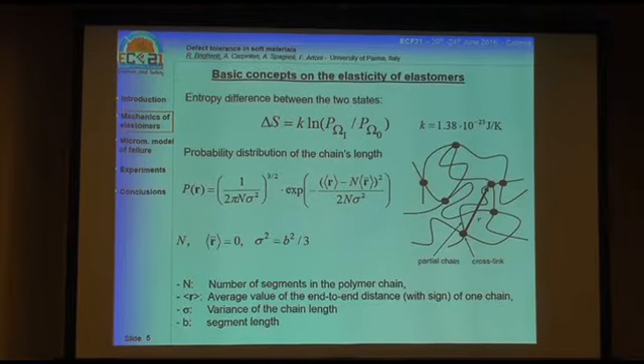So typically, this kind of material is described by the classical rubber elasticity theory that takes into account the probability distribution of the so-called R² distance, which describes the average distance between the crosslinks that exist between the polymeric chains. This is the standard probability distribution used in this case, which is a Gaussian. We have several parameters: the number of segments that compose a single chain, the average distance between the two ends, and the standard deviation of the distribution of the chain segments.